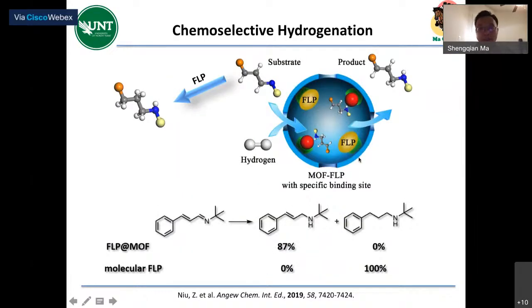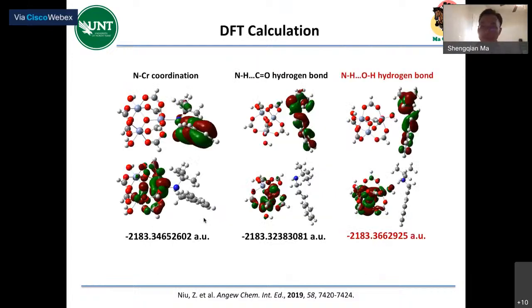So this is the ideal: if we just use a homogeneous system, they're going to reduce both the carbon-carbon double bond and the imine bond. And when we put in a MOF with an activation group, it's going to preferentially and selectively reduce the imine bond. And as we expected, when we put this FLP in the MOF with a fraction of hydroxyl group and open metal site, we achieved chemoselective hydrogenation that reduces just the imine bond, but not the carbon-carbon bond. But this is not the case for molecular FLP. They reduce both the carbon-carbon double bond and the imine bond. So this is a very interesting chemoselectivity because of the tailored microenvironment in the MOF, which is not achievable for